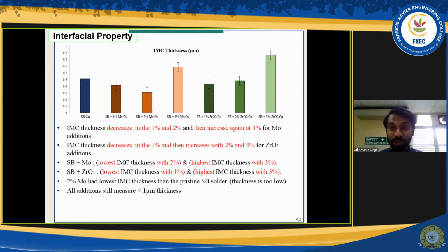For zirconia, there was an increasing trend, but the first 1 and 2% had a lower IMC layer than the SnBi, but the 3% addition had quite a hike. But it could be really satisfying because if you look at the scale here, this is measured in micrometers. That means the highest that could be obtained for the 3% zirconia is still less than 1 micrometer. Other studies have shown that 2 to 3 or 2 to 5 micrometers of IMC layer thickness is enough to give a proper strength. But what we are producing here is actually less than 1 micrometer. So we are actually preserving a very much thinner IMC layer.